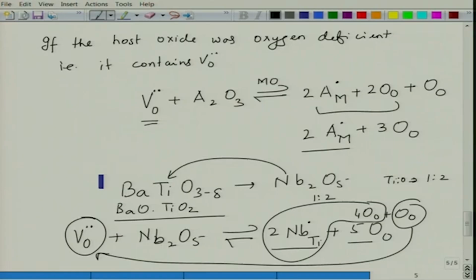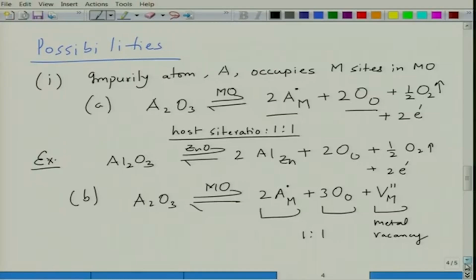Okay. So, barium titanate may have electronic defects, it has oxygen vacancies. So, how do you eliminate oxygen vacancies? You bring in extra oxygen into the system by doping it with an oxide of higher valence. This is called compositional engineering of oxides. So, not only impurities can give you defects, but impurities can also be used to compensate the defects which exist from earlier.